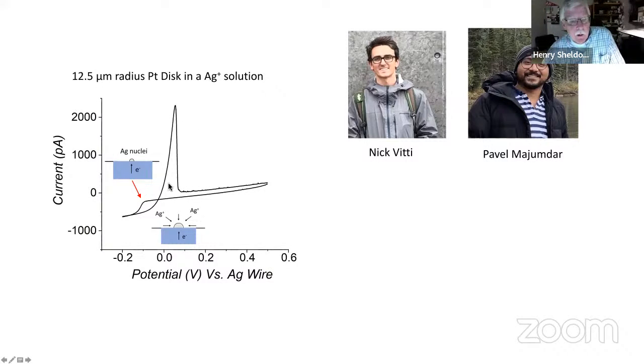And the experiment, this voltammogram here, is looking at the deposition of a silver particle on a platinum microelectrode, a small electrode. Okay, and so the CV, this is very classical. You scan negative, and there's a little sloping background curve here that's not important. But you get out here to this point, you nucleate a silver particle, so there's a nucleus formed, and the particle starts growing. You get a limiting current because you're limited by silver ion being transported to the particle where it's deposited, and then you can come back and strip it off. Okay, and so that's been in the literature for 80 years, I suspect.